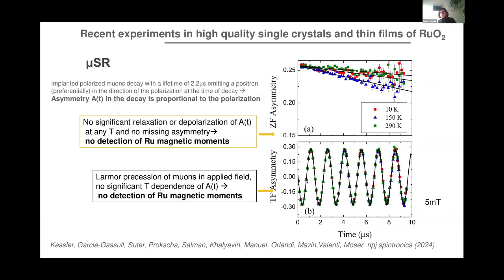The second measurement was done in the group of Simon Morza, and these measurements were done, as far as I think, at ISIS. So that's mu-SR. The idea, as you know very well, with mu-SR is that you implant polarized muons, and they decay with a certain lifetime of the order of 2.2 microseconds. Then they emit a positron, which is preferentially in the direction of the polarization, if you have a polarization in your system. What you measure is the asymmetry in the decay, which should be proportional to this polarization. Here I'm showing this asymmetry in two measurements, a zero field measurement, and then applying a magnetic field of the order of 5 milliteslas.